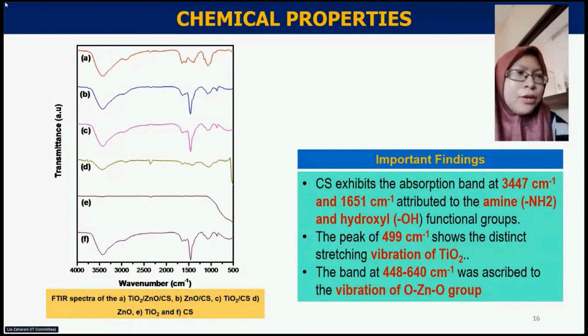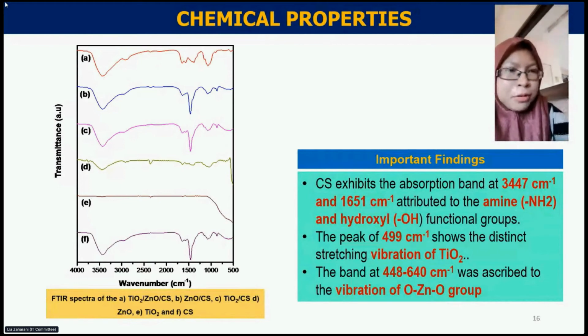The peak in the range of 1000 to 1600 is ascribed to the bending vibration of the primary amines and stretching of the carbonyl groups. The intensity of this peak in the titanium and chitosan has been attributed to the lower availability of the free hydroxyl and primary amine groups of chitosan and their involvement in the bonding with the TiO2. These groups serve as coordination and reaction sites for the absorption of the organic compounds.